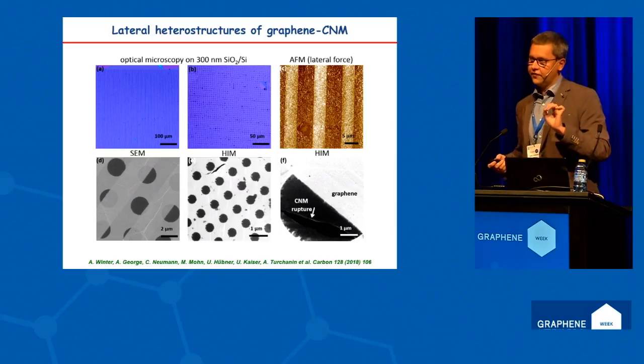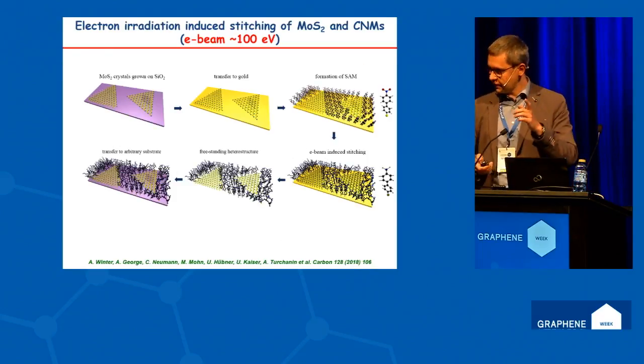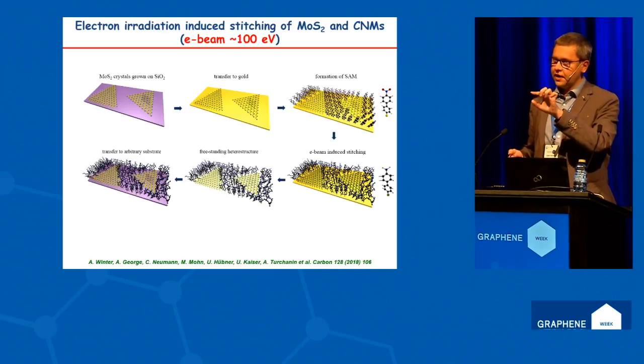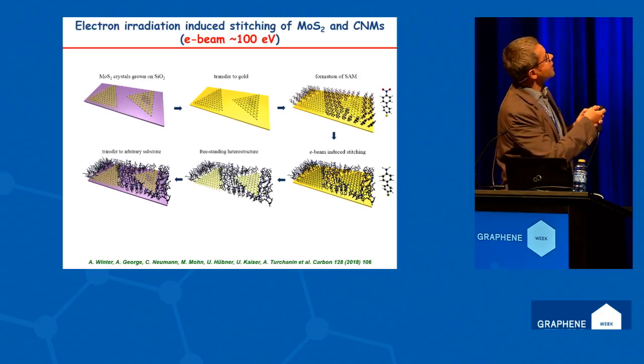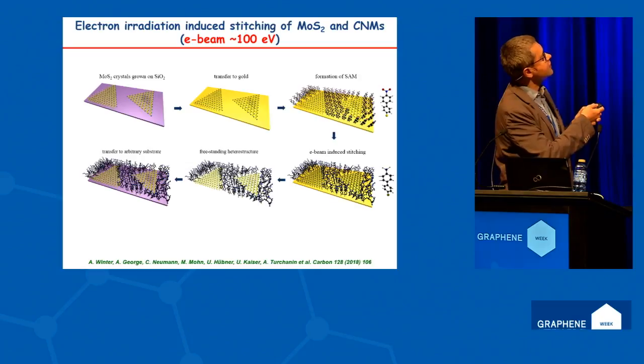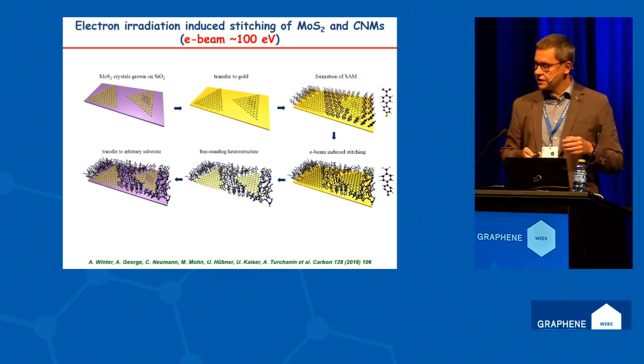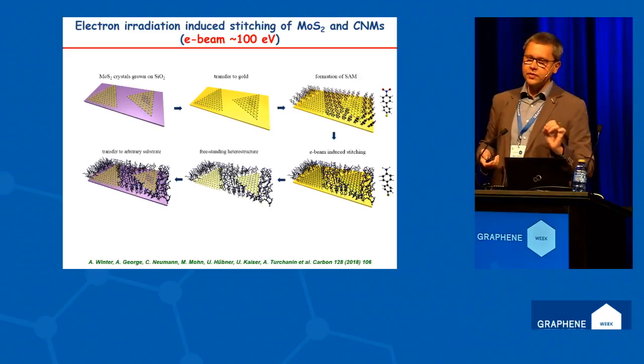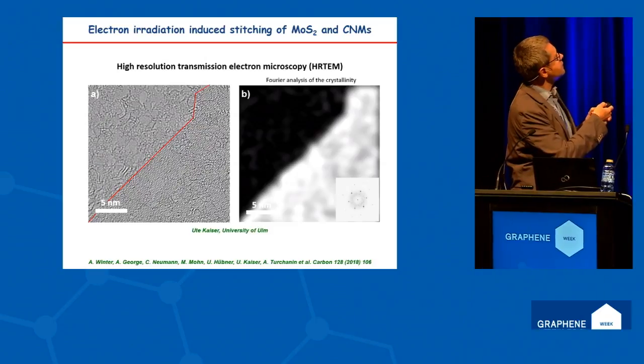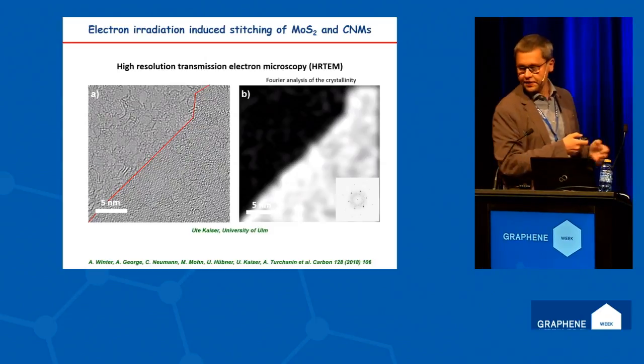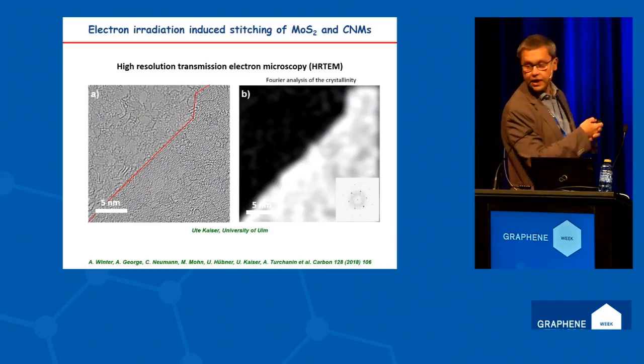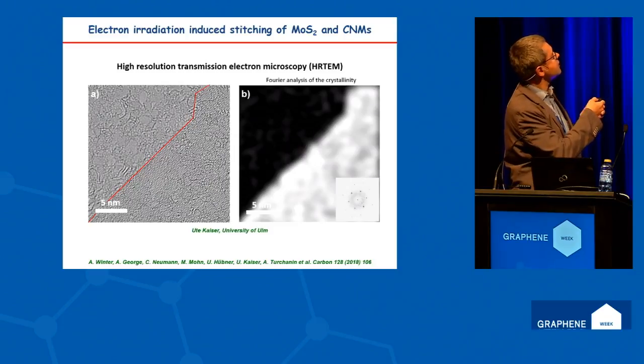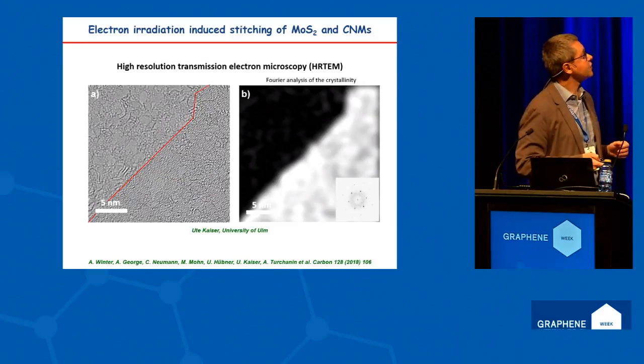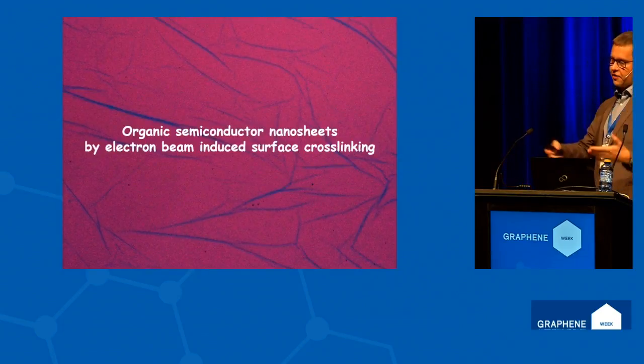These heterostructures form very sharp atomic edges, and I would like to demonstrate this with another example. This is now the heterostructure between carbon nanomembrane and molybdenum disulfide, where you again use CVD grown molybdenum disulfide. You fill the free areas with the respective molecular precursor, and then you cross-link it with an electron beam. If you analyze how atomically sharp the edges of these materials are, you will see with this high-resolution transmission electron image, acquired in the group of Ute Kaiser, that they possess nearly atomic sharpness. You can see very well this grain boundary between the short-range ordered molecular carbon nanomembrane and the very well ordered molybdenum disulfide.